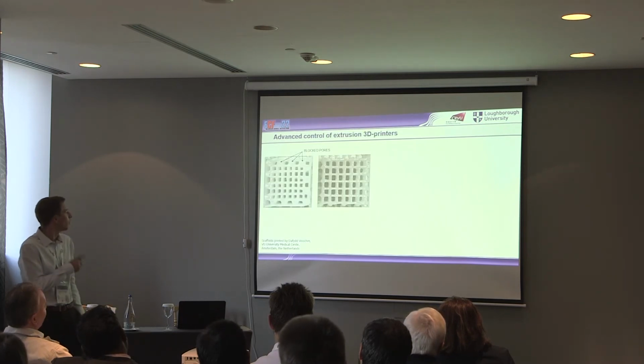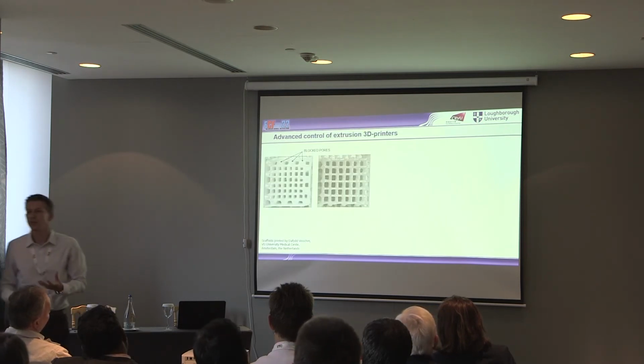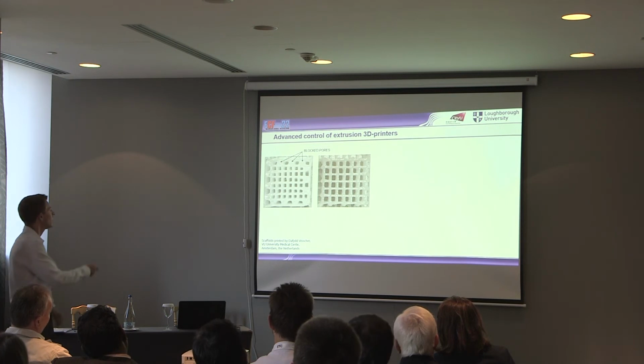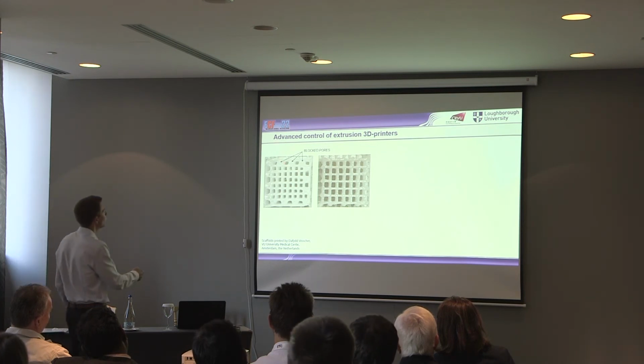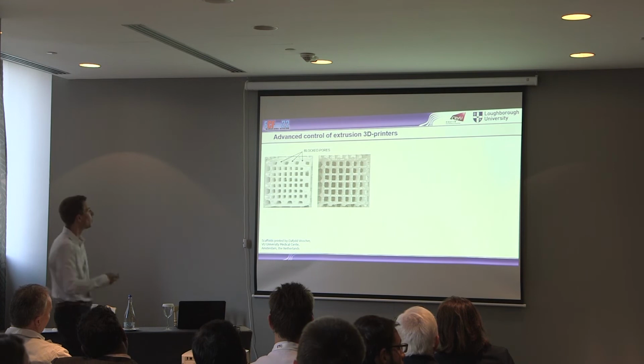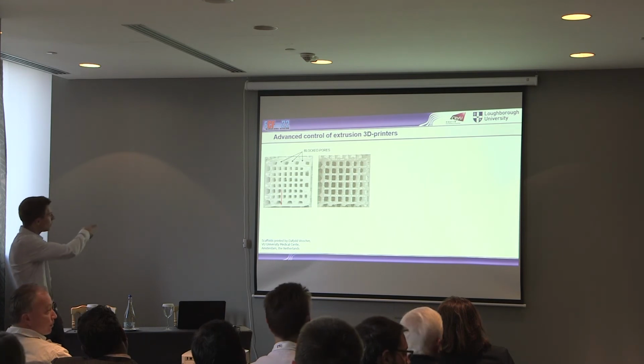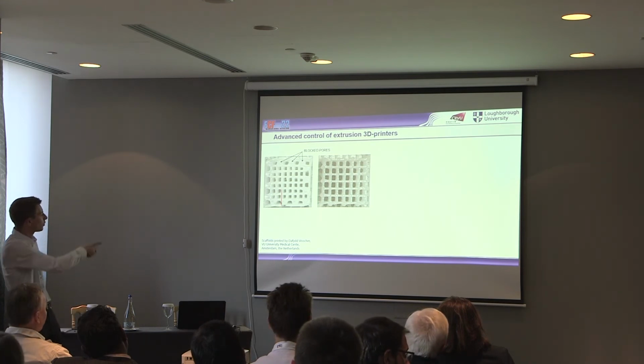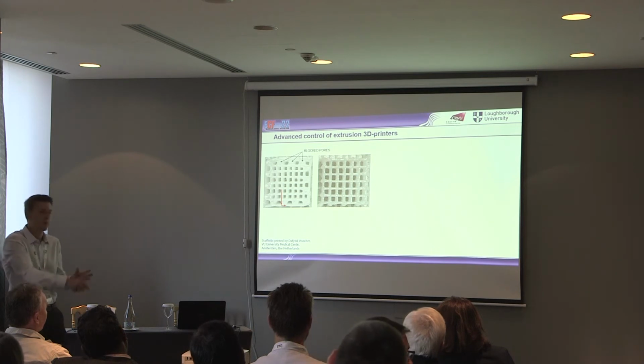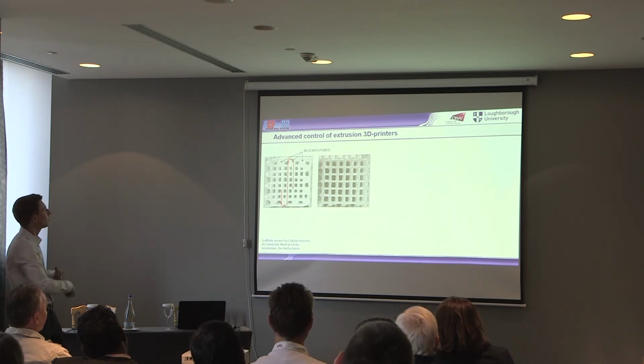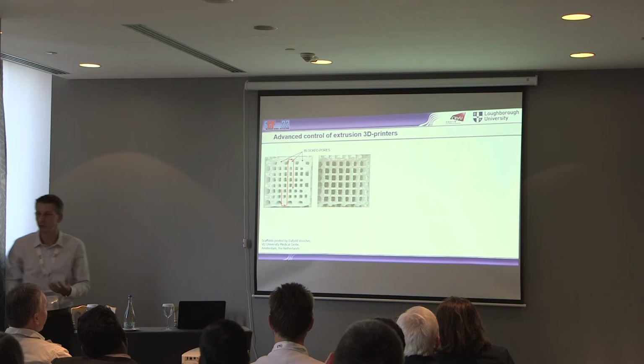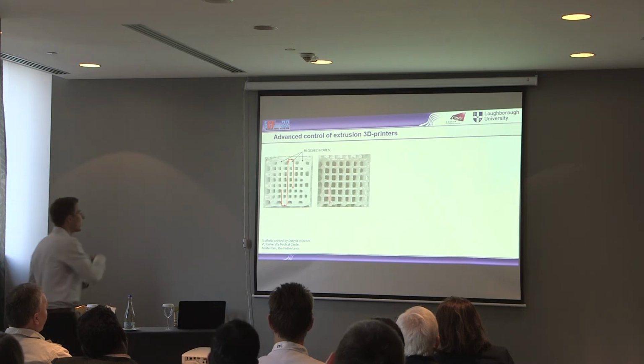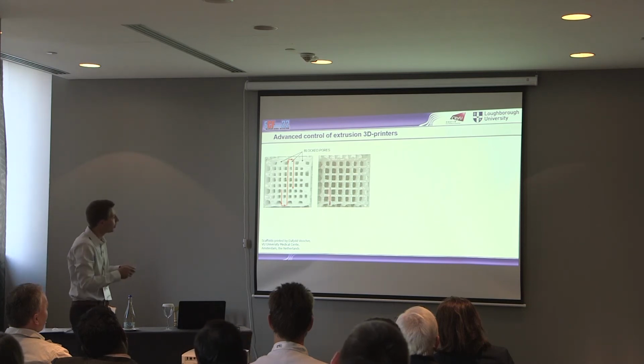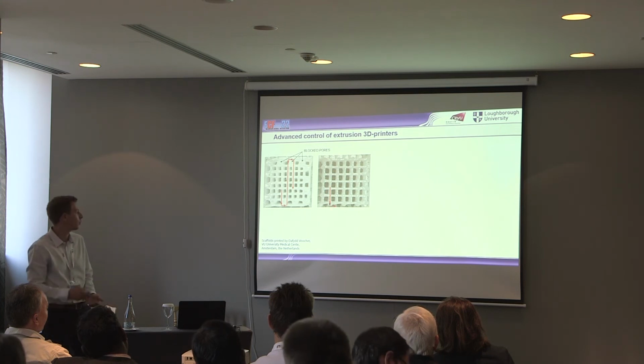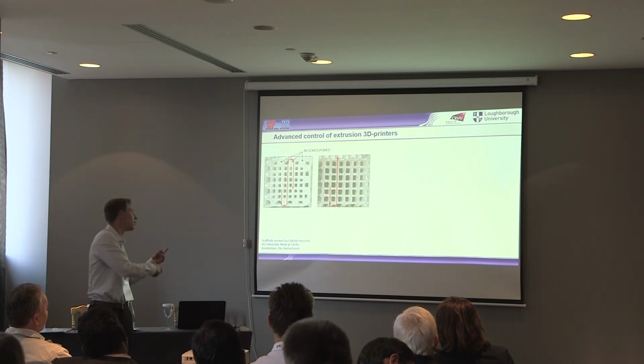Just an example of a separate advanced control of the 3D printer. Let's say this is a tissue engineering scaffold, and you can see we've got these blocked pores at the top. The way this was printed, the 3D printer nozzle comes down, moves across, dragging that polymer into that pore, and then moves to the other side, moves across, and it's dragging the polymer and blocks those pores. A super simple change, just coming down and then a little step outside before we move across. Go to the other side, a little step outside, go across.